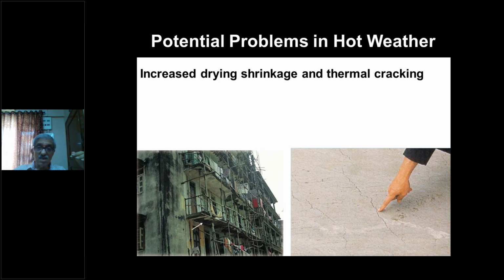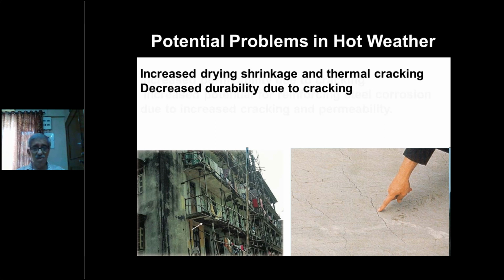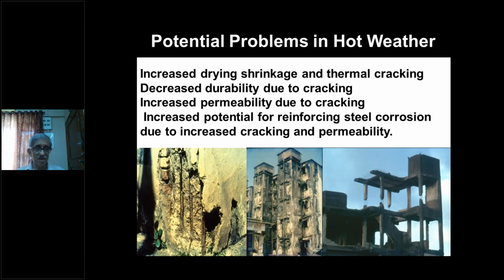Also, as the temperature inside the concrete increases, there is a thermal differential between the concrete and the ambient temperature, and therefore again thermal cracking can also take place in hot weather. This cracking business reduces the durability of concrete. It may not structurally initially harm the concrete strength, but later on, yes. An increased potential of reinforcement steel corrosion due to increased cracking and permeability becomes a nightmare for the people staying in the buildings like this.